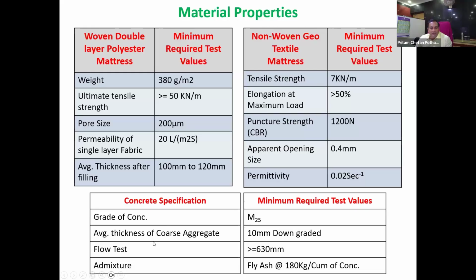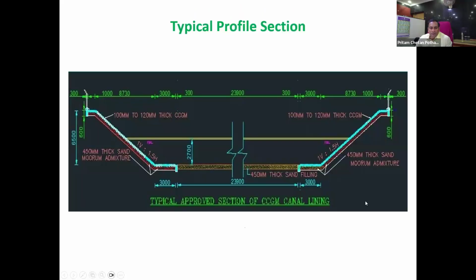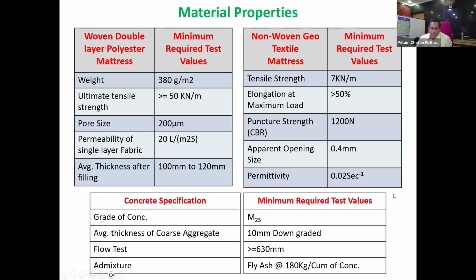and the concrete grade we are using is M25. Average thickness of coarse aggregate: I told you it is micro concrete, that's why 10 mm and below. And since we have to pour the concrete through pressure within the CCGM, we are not using the slump test, because it is a flow concrete. That's why we are testing with the flow table test, which should be greater than 630 mm. As admixture we are using fly ash.